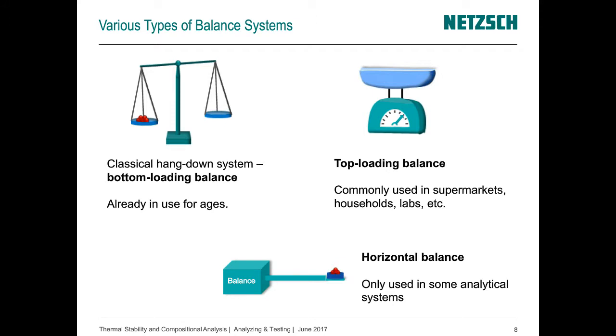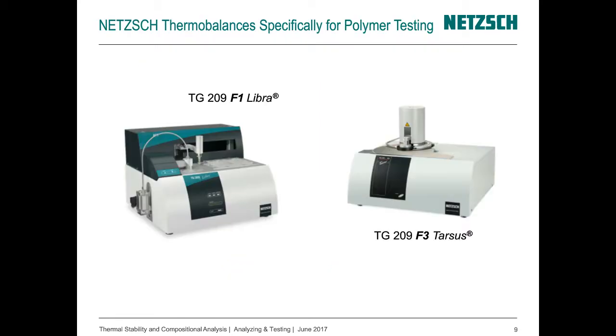And here in the next slide, we can see two representatives of the Netzsch thermobalance line, specifically dedicated to polymer testing. On the right side, you see the so-called TG 209 F3 Tarsus. It's the workhorse for polymer testing with a temperature range between room temperature and 1000 degrees C. On the left side, you see the TG 209 F1 Libra instrument. This is the premium instrument of this polymer testing series, and it has an upper temperature limit of 1100 degrees C. It has a robust ceramic furnace, and what is really brand new, an automatic sample changer for high sample throughput, because it has two trays in microplate format with up to 192 positions.